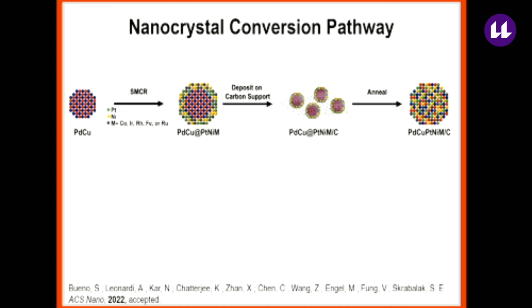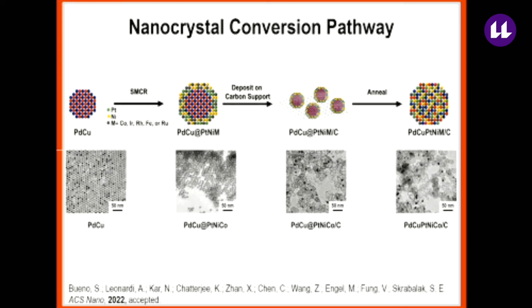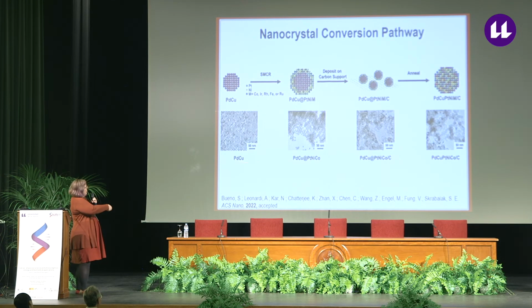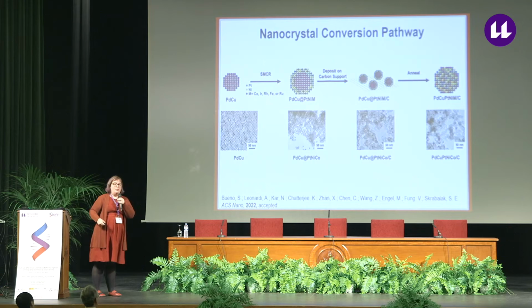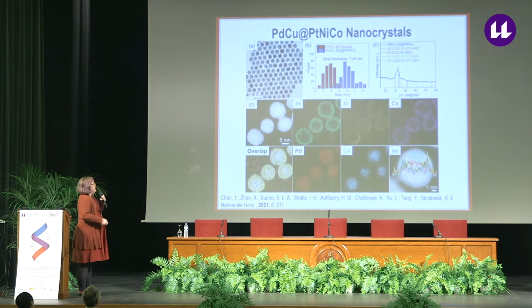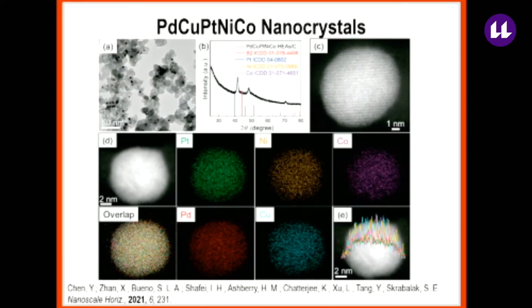We take those core shell nanoparticles and deposit them onto a carbon support, heat them up to high temperature to facilitate interdiffusion and mixing to make the mixed alloyed phase. A nice outcome of this is that you can start with very monodispersed seeds, and that monodispersity gets transferred the whole way through to the high entropy composition with the 5 different metal elements. And so shown here are the initial precursor core shell nanoparticles, where we started with palladium copper in the interior, platinum, nickel and cobalt in the shell. You can see the core shell architecture here. We heat them, and now all of the elements are mixed at the atomic scale. We have a single phase by powder diffraction, also by high resolution TEM.